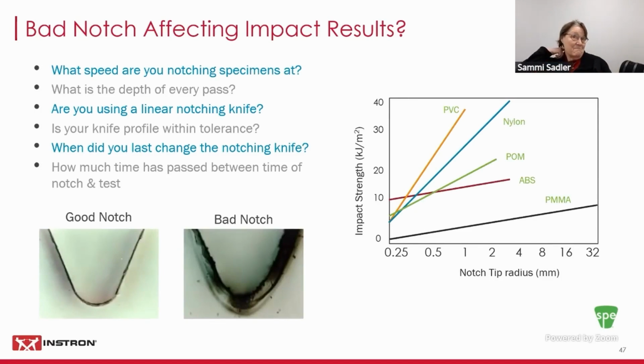So, here at the bottom, on the left is a good notch. On the right is a bad notch. The good notch, if you look, you see it's nice and clean on the sides. It's clear down in the apex and the bottom of the radius. The bad notch shows signs of being overheated. The discoloration on the sides of the V. You see that the material actually has melted and collected at the bottom of the notch.